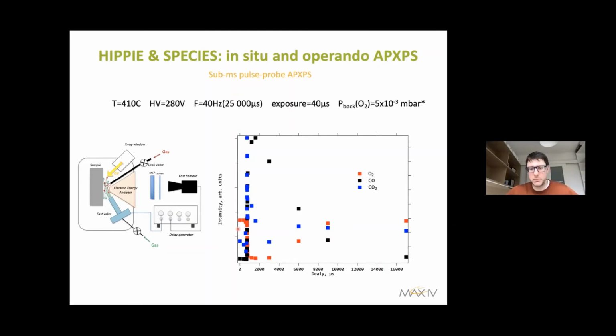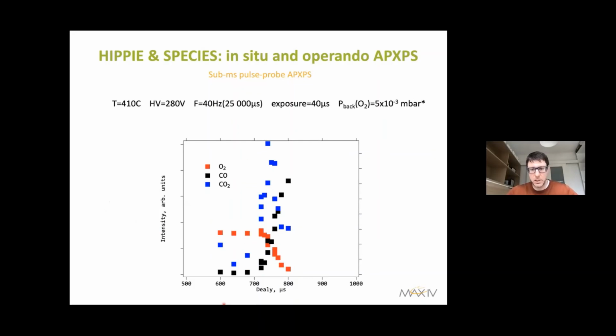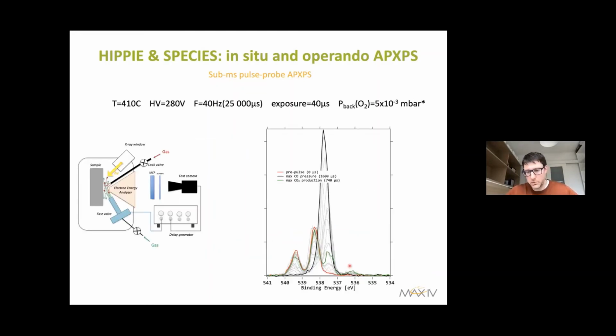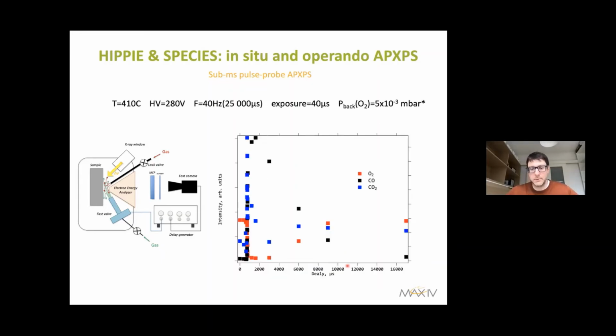This is the example from the fit. You can see the CO pulse now is very long, about 5 to 6 milliseconds. But if you focus on this area where the transition happens, it's about 100 microseconds. So the transition between oxygen-rich conditions to CO-rich conditions happens in only about 100 microseconds. The blue data here is the production of CO2. So sorry, if you look here, we do have a production of CO2, and it's non-negligible within the pulse.